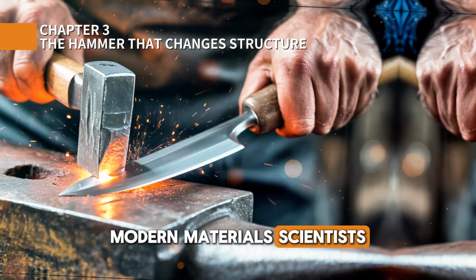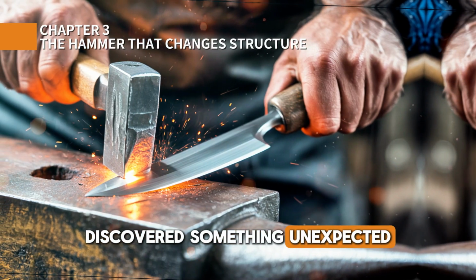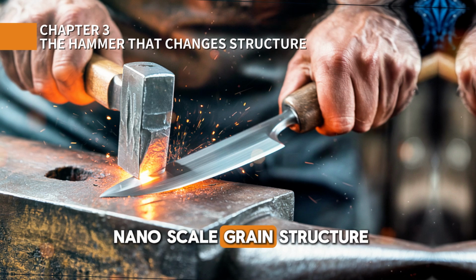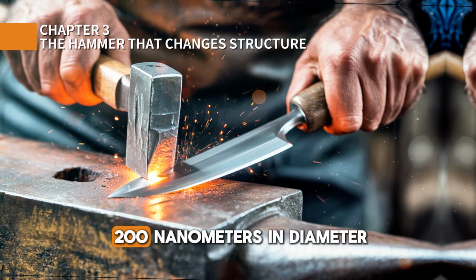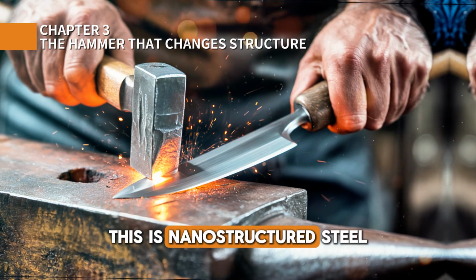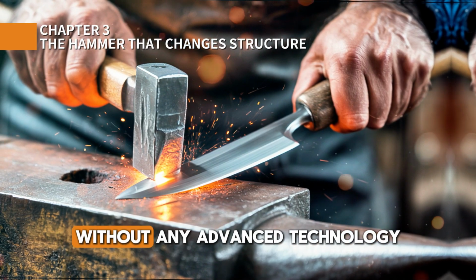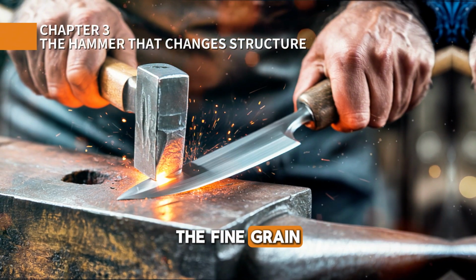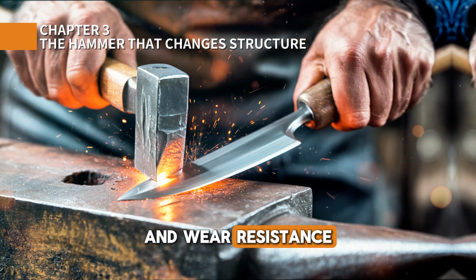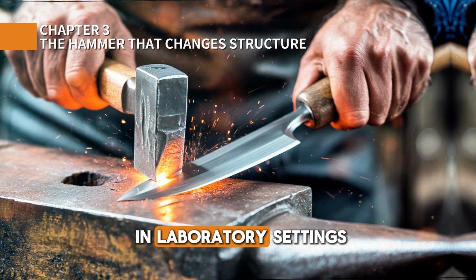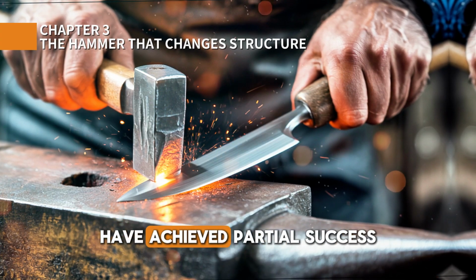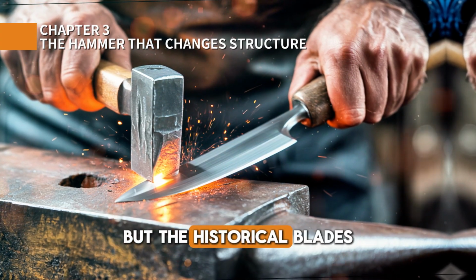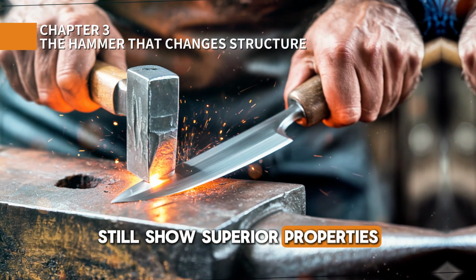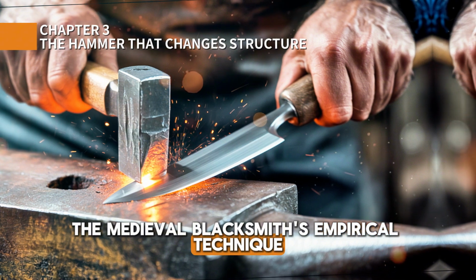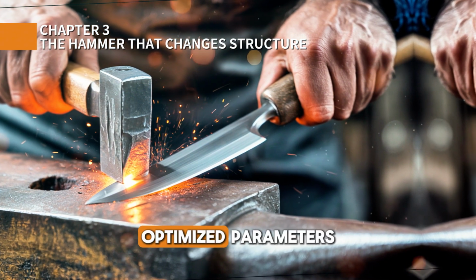Modern materials scientists studying medieval blades discovered something unexpected. The peened edges showed nanoscale grain structure, crystals just 50 to 200 nanometers in diameter. This is nanostructured steel, produced through mechanical processing without any advanced technology. The fine grain structure provided extraordinary hardness and wear resistance. Attempts to reproduce this in laboratory settings, using modern hammering equipment, have achieved partial success. But the historical blades still show superior properties. The medieval blacksmith's empirical technique, refined across generations, optimized parameters that researchers are still trying to fully understand.